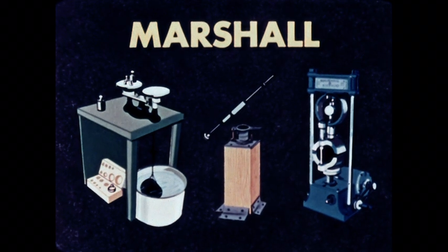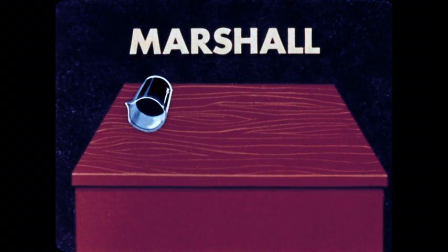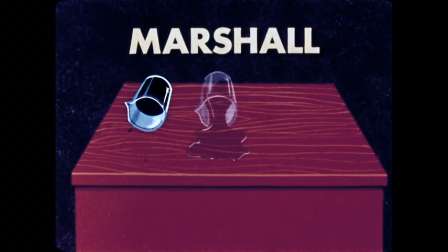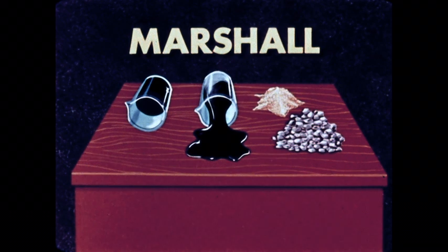The Marshall procedure is a series of tests which, if properly performed, will accomplish the objectives of good paving mix design. The Marshall procedure for designing hot mix asphalt paving may be used for laboratory design and for field control of mixes made with asphalt cements. It has not been standardized for mixes containing liquid grades of asphalt, nor for mixes which contain aggregate exceeding 1-inch maximum size.